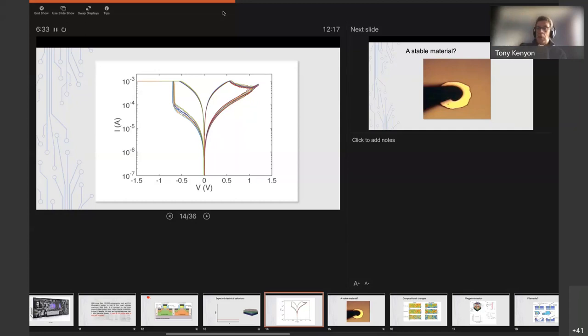And that means when you electrically bias your device, there's no preference for the device to electroform in one polarity or the other, and it's purely symmetrical. And that isn't necessarily where you want to be. You probably want some asymmetry in the system so that you get a nice differentiation between going from high resistance to low resistance and low to high, and you don't get these competing electroforming at both polarities. So you need to build, ideally, some degree of asymmetry in. That means you probably want a different metal top and bottom.